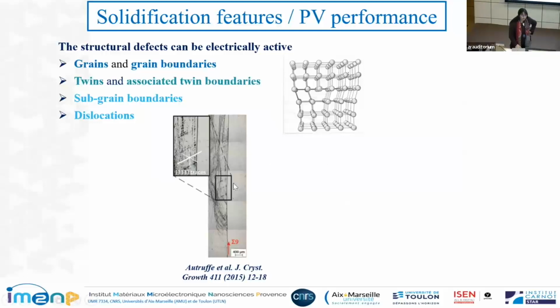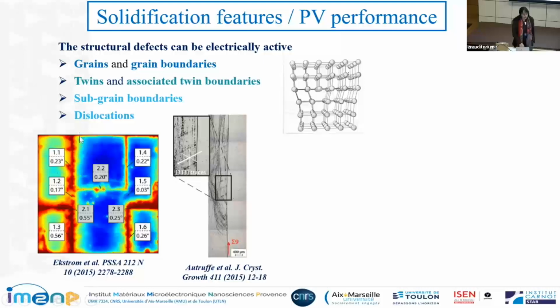Here you have dislocations that developed during the growth of an ingot in a casting process where they use some monocrystalline seeds at the bottom. But as they are very big ton ingots, you cannot have a very big monocrystalline seed, so you use several of them, and you have some edges between these monocrystalline seeds and the formation of dislocations here, and it degrades the electrical properties.